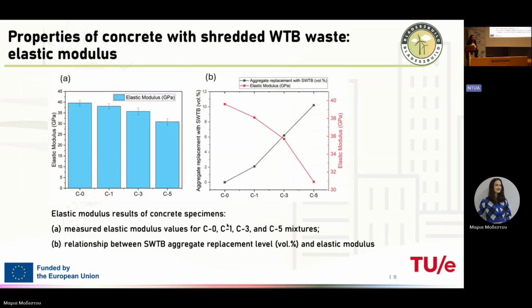For other properties, because we try to describe the deformation, fracture, elastic modulus of the material, as well as durability aspects. So here is the elastic modulus result of concrete specimens. They are mostly a bit lower for higher dosage of wind turbine blade waste, but for 1% and 3%, it's comparable to the control one, and not below 30 gigapascals.